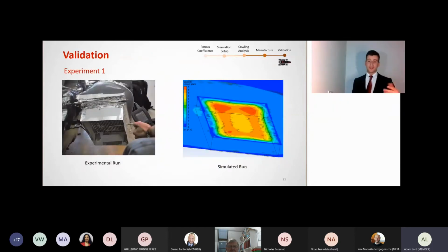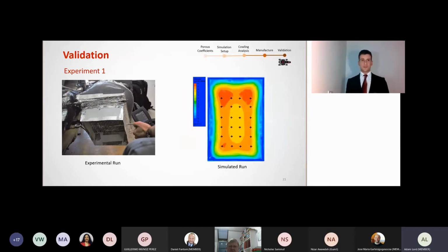Now, a critical part of any computational simulation is the establishment of a reasonable amount of confidence in the results obtained. And so validation of the CFD simulations in this project was done in two parts. The first part consisted of a non-invasive experiment, which was focused on finding an area-weighted average of the velocity of inflow through the radiator, and a hot wire anemometer was used to record the inflow air velocity at several marked points on the radiator face, as you can see in the picture here.